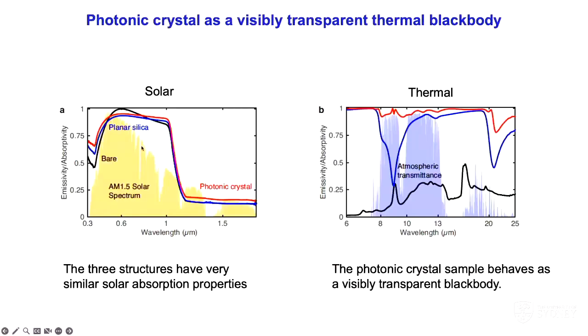On the solar side of the wavelength range, the three structures absorb very similarly. You can see this characteristic absorption of silicon that cuts off around 1 micron or so. The photonic crystal structure in fact has slightly higher absorption because of a light scattering effect. On the other hand, on the thermal side, the three structures behave very differently. The silicon, as I mentioned, doesn't emit much. The flat silica structure has strong thermal emissivity, as indicated by the blue line here, but it has a very large dip due to reflection right in the transparency window. And the presence of the photonic crystal removes this dip to give you a completely flat, near-unity thermal emissivity over a fairly wide wavelength range.